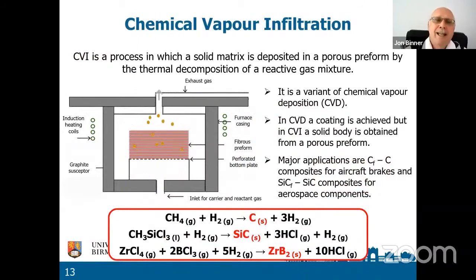Chemical vapor infiltration. It's a process in which a solid matrix is deposited in a porous preform by the thermal decomposition of a reactive gas mixture. So you pass a gas at high temperature through a fiber preform, the gas breaks down and deposits a solid. And you can see three different chemical reactions there. Methane breaks down to give you carbon. A rather nasty gas called methyl trichlorosilane breaks down to give you silicon carbide. And zirconium chloride, together with boron chloride, breaks down to give you zirconium diboride. And you've got many, many other chemical reactions that will also work. The process is a variant of chemical vapor deposition, which more people have heard about. In CVD, you get a coating, but in CVI, you get a solid body from a porous preform.